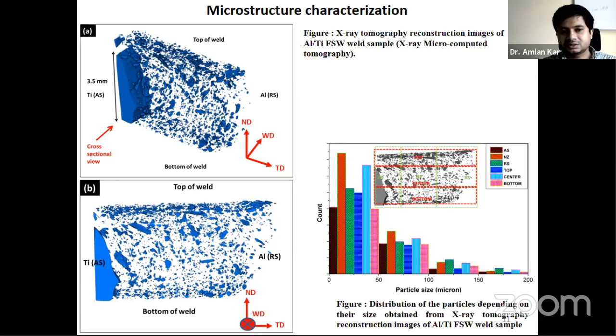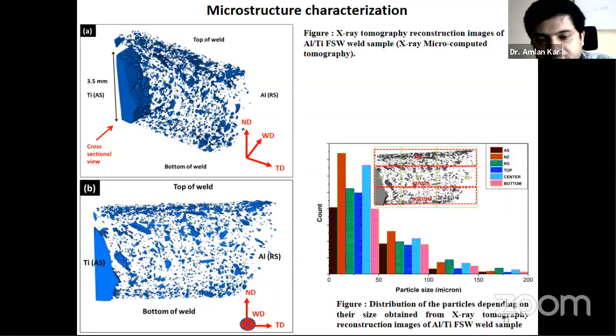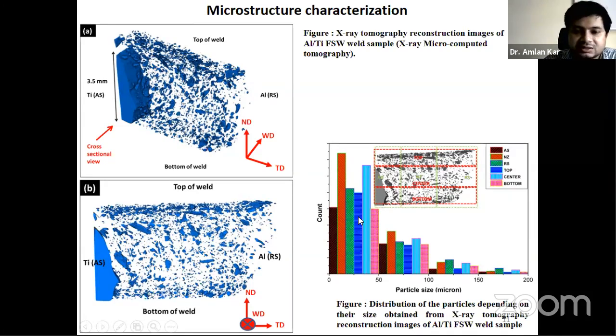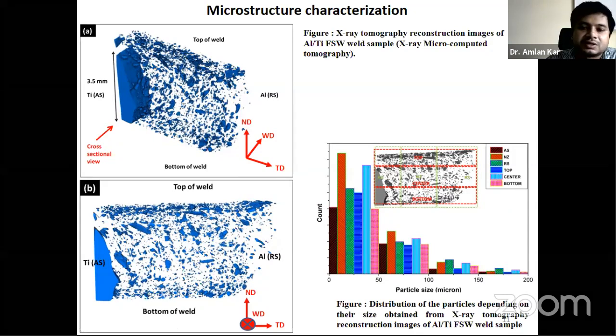And even though they are more or less haphazard, one thing we have seen is that the deformation behavior or the fragmentation behavior of the titanium has some similarity. What is the similarity? When the particle size reduces continuously, at each location there is an increased fraction or increased number of counts of the particles. In other words, the very fine particles in each location are present in greater numbers compared to the particles with higher size dimensions. Okay, so these are the observations.